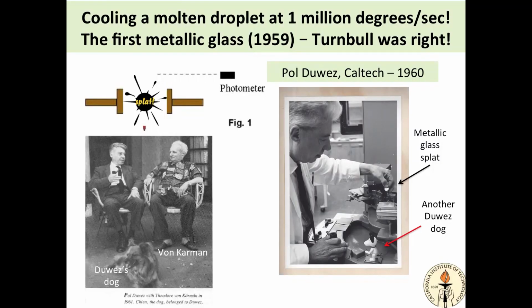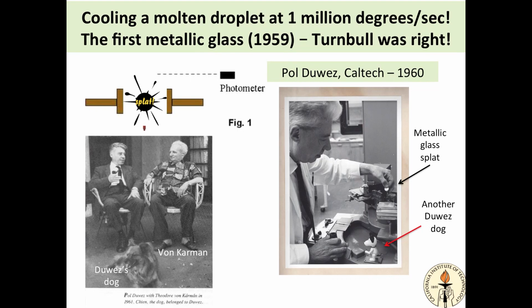Well, it was previously thought that metals don't make glass, but my advisor back in the 1950s, Paul Duwez, is shown here with Theodore von Karman, who was a pioneer in aeronautics here at Caltech. He hired Paul in the 1930s. Paul was Belgian. So Paul developed something called splat quenching. He took a piston and an anvil and dropped a droplet of metal alloy and smacked it. And the anvil and piston are made out of copper. They conduct heat really fast. And he figured out that you could cool a metal at 1 million degrees per second by splatting it. It's called splat quenching. Well, he started splat quenching metal alloys and shortly discovered that some of them form glass.